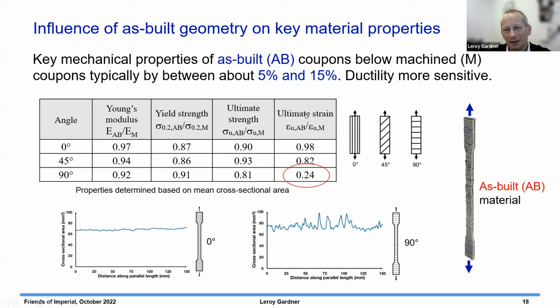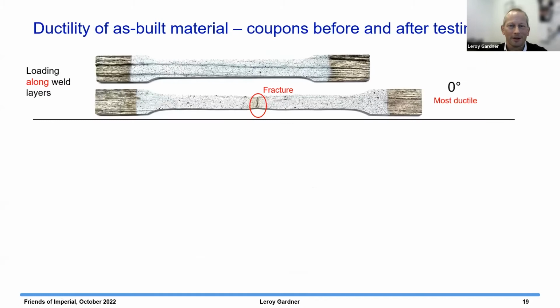But over here, this ultimate strain, this is a measure of the ductility of the material, you have a more severe reduction in the 90 degree direction. And 90 degrees is where you're pulling across the layers. And so this material is affected quite strongly by the direction of loading. And what's going on, you can see on these photos.